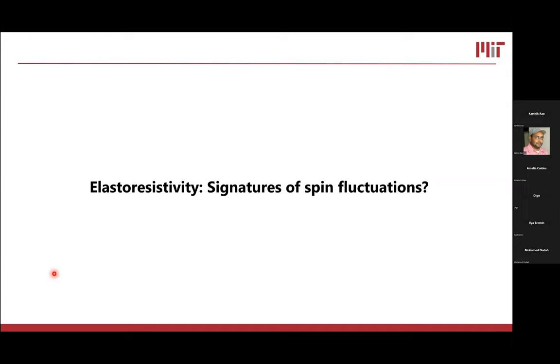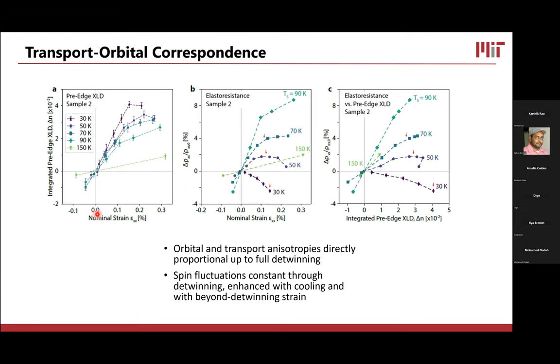Then this gets us to the encore of the talk, which is to look more carefully at the elastoresistivity. If I take this XLD data that I just showed you as a function of temperature, I can compare that to the resistivity that I measured at the exact same time that this data was being taken. And that gives me this data here. So this is XLD versus strain, and this is resistivity versus strain. And just looking at this by eye, you can see that there's some similar shapes here, but they actually invert as a function of temperature.